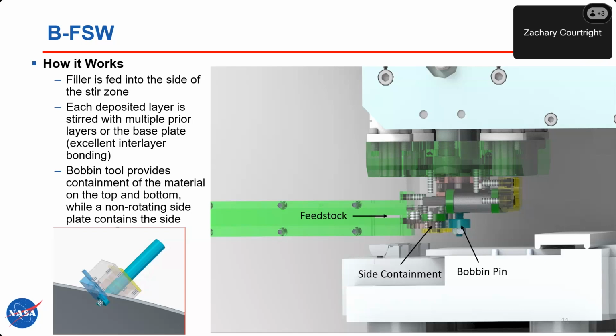In this configuration, like I said, it'd be about an 1/8 inch per pass, and the pin tool was 1 inch diameter. So for every single pass, you would be stirring seven of the prior passes, in addition to one new pass. So it's mixing that all in, and you get really good adherence to prior passes. At a lab scale, we were able to demonstrate that with an 1/8 inch deposition, which is already an order of magnitude greater than pretty much anything else out there.